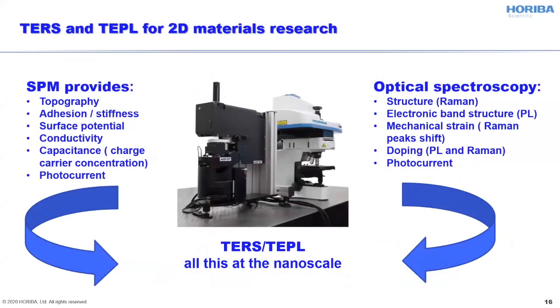So for 2D semiconductors, scanning probe microscopy can provide a fairly extensive list of information. So of course, topography, and if you look at all the publications on 2D materials, practically every single one has at least one AFM image. So we can probe adhesion, stiffness, surface potential, which is very important actually, conductivity, capacitance, photocurrent across the 2D sheet.